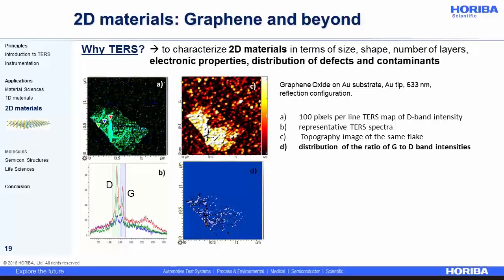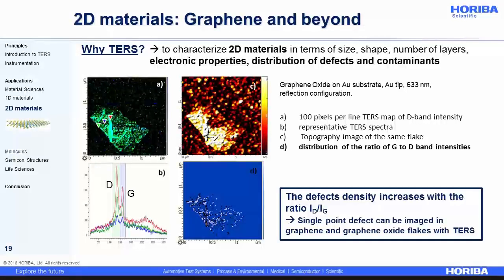Maybe more interesting is the figure D on the bottom right, where we show the distribution of the ratio of the G to D band intensities. This is what is used generally in Raman spectroscopy in order to locate precisely the defects on the graphitic structure. So you have to know that TERS is extremely sensitive to single point defects, and those point defects can be imaged in graphene and in graphene oxide thanks to TERS.